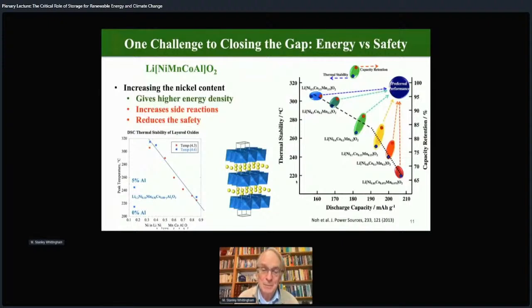And I should emphasize, we never expect to get to these temperatures. But this thermal stability is a direct measure of how reactive these materials are with the organic electrolytes. And I show on here, this is where you want to get to, 100% capacity retention and the highest energy. And you can plot this peak oxygen evolution temperature versus the nickel content. And it's essentially a straight line, independent of how fully charged the system is. So what we have to do is really modify these systems so we can increase the energy density, eliminate any of the side reactions, stop this oxygen evolution.